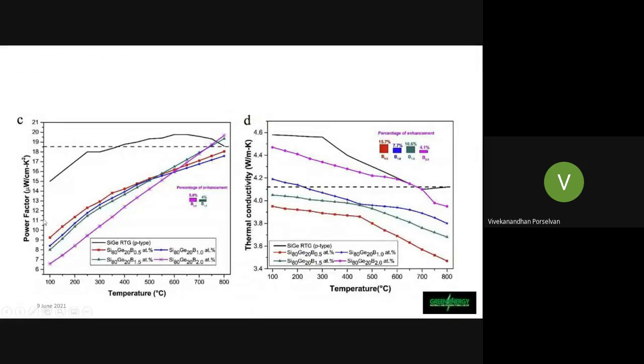And this is the power factor of silicon germanium alloy which is doped with boron. We can see that this is showcasing a very good power factor compared to the alloy which is being used in space, that is, the RTG sample.